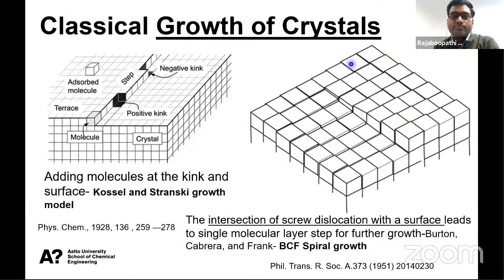So this is the theory, and we are applying two models to explain the further growth of the nucleus. One is the Kossel-Stranski growth model, or we can say layer by layer growth, and this one is spiral growth. In layer by layer growth, after forming the nucleus, there may be kink sites, positive kink, negative kink, or adsorbed molecules, and based on the surface free energy or the Gibbs free energy of the system, the next layer or next molecule will attach here or here. So we can say addition of atom by atom or molecule by molecule, or simply a layer by layer growth.